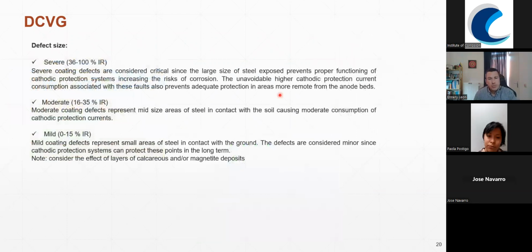One of the advantages of this survey is that you can get quantification of the damage, of the defects in the coating. So you can say, okay, all those defects that are around 36 and 100% IR, sorry, they are quite large, and usually they need to be taken care of, in the sense that you want to excavate and repair them. Those that are between 16 and 35%, they are moderate, and they might be okay depending